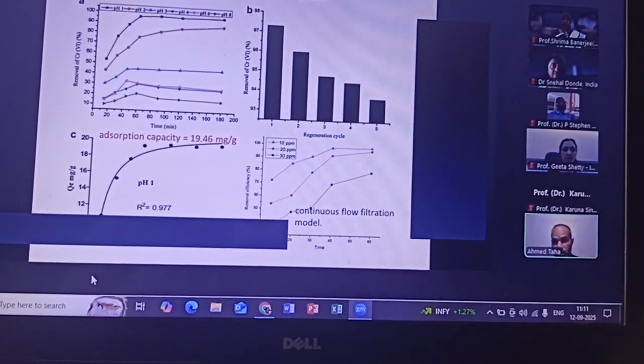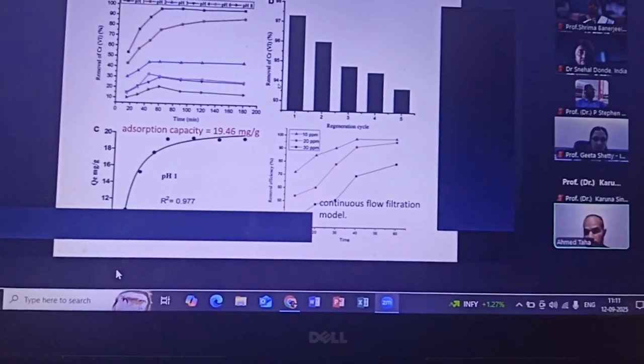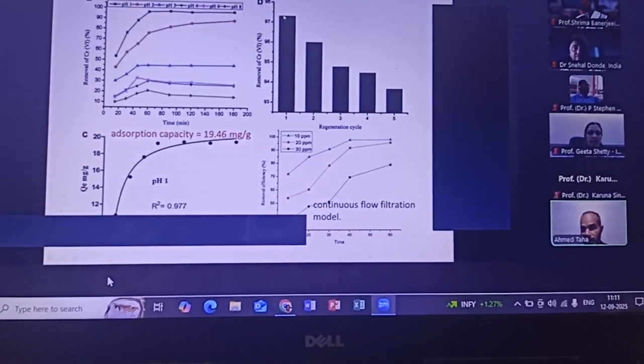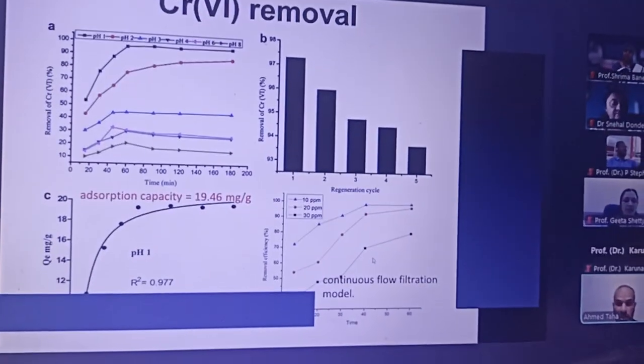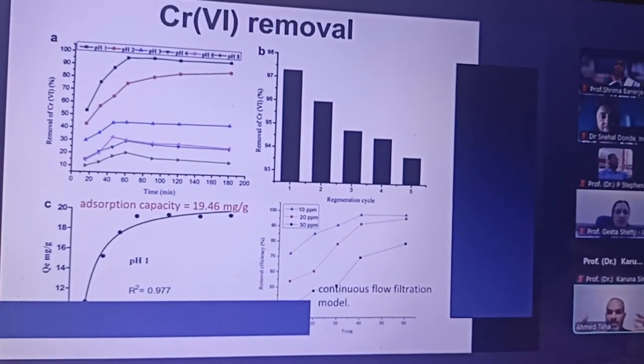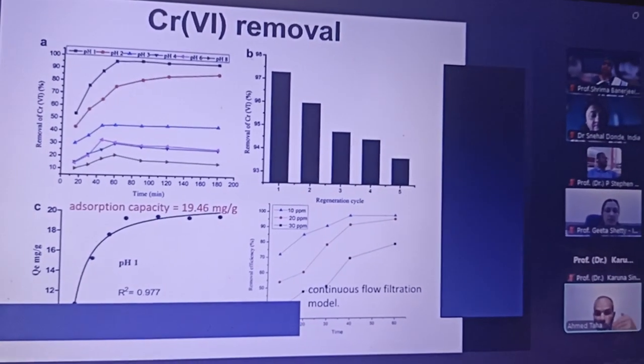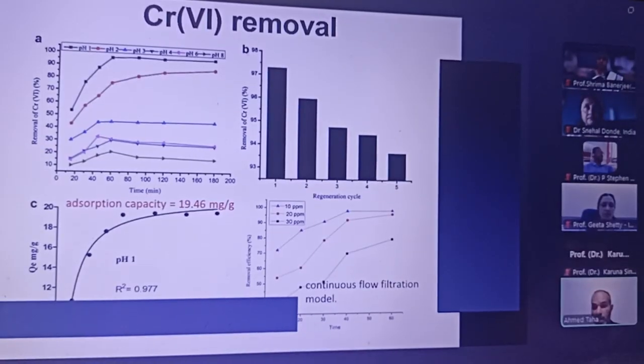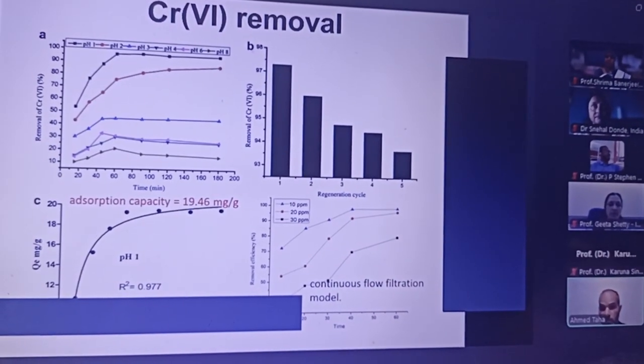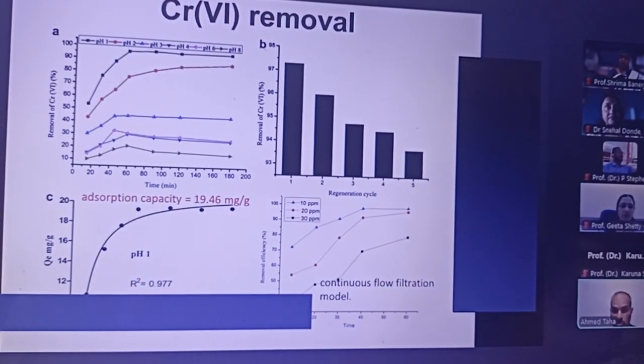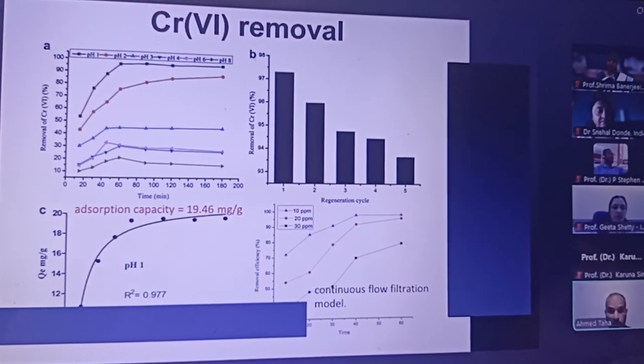This is the amount of heavy metals removed by each gram of this material. We also did recycling to see if we can reuse the material, and the efficiency stayed quite high, from 98 to 95 or 94%. It's a little bit of a drop, which is normal. We also studied this material in a continuous flow experiment. We have a setup with the membrane, and we take the water through this membrane and out, and we check it over many cycles, and we found the performance is quite sufficient.